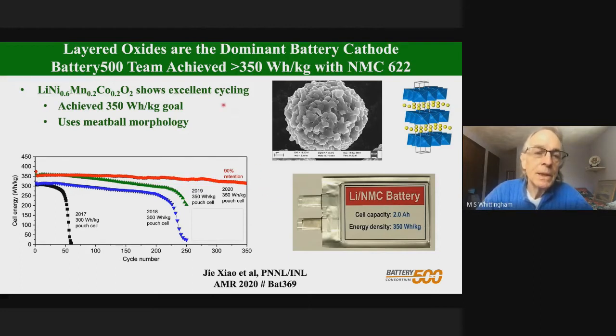The material we use for these tests is 60% nickel, and it's formed in these what we call meatball morphologies. So you can see the primary particles here are maybe 200 to 300 nanometers. They're then formed into these secondary particles of about 5 to 10 microns. We need these large secondary particles so it packs better and gives us a higher density. So here's the data we've got so far.